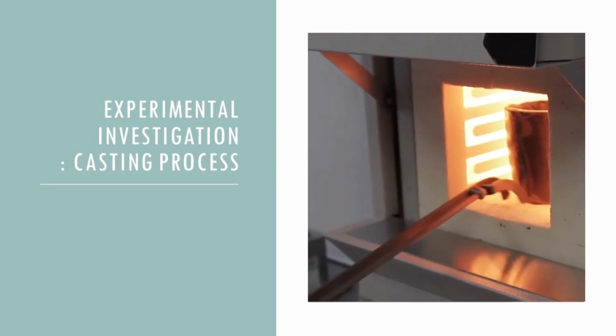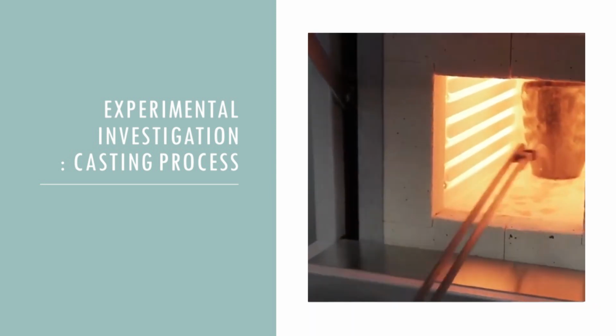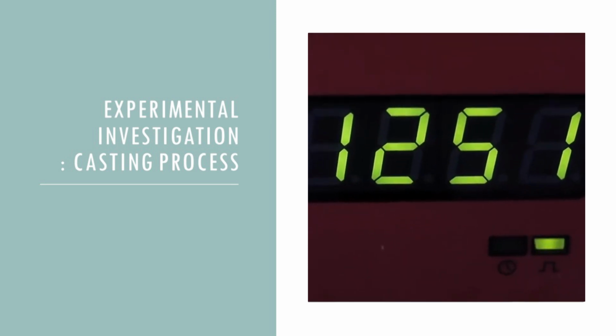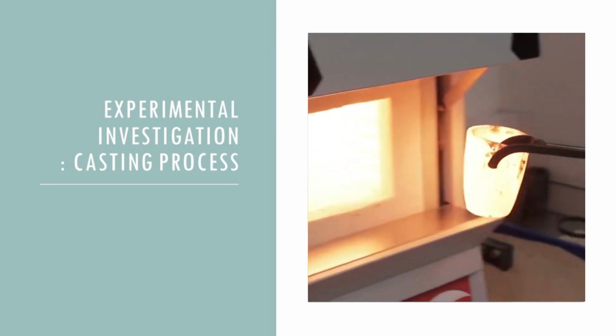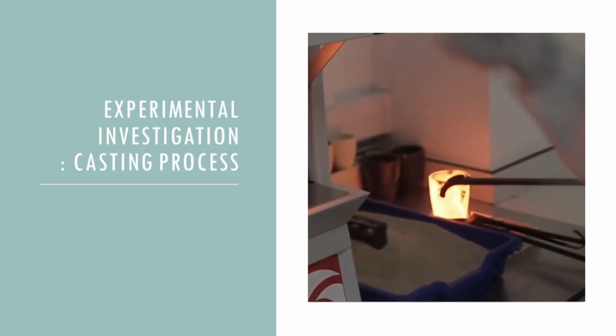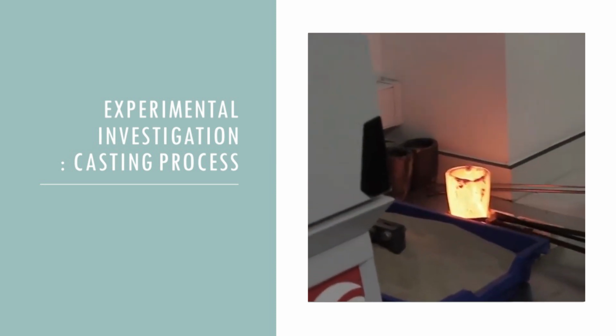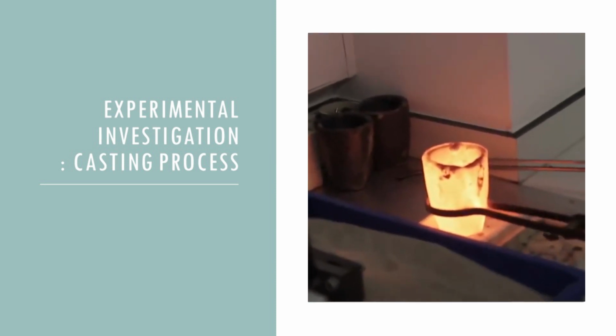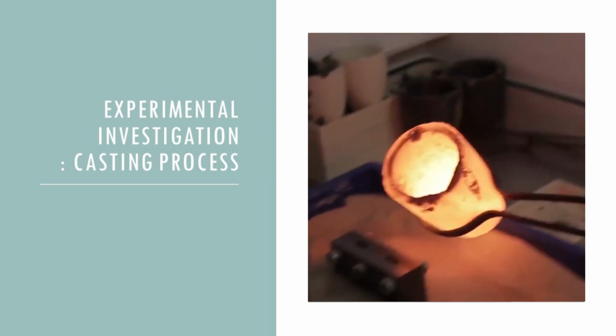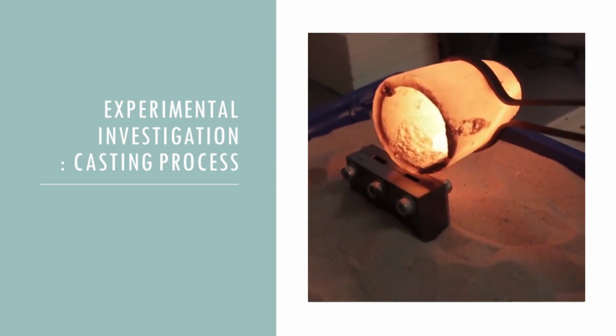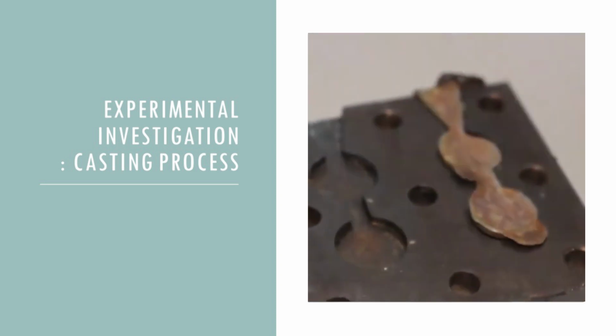All of the moulds were preheated to 350 degrees in a drying oven, to prevent rapid cooling of the molten metal upon contact with the mould, which would spoil the casting. The alloys were melted in the furnace at 1250 degrees for 20 minutes and then poured. Following this, after the flans had cooled, they were removed from the moulds.